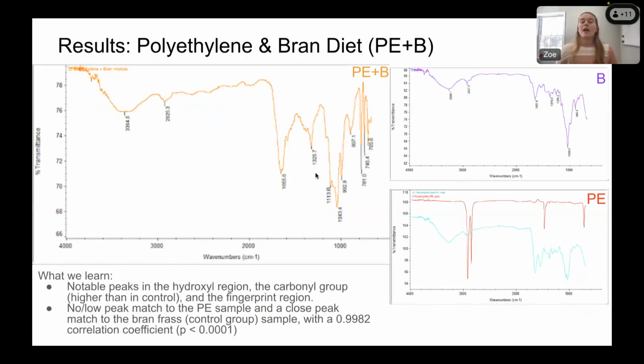The polyethylene and bran mixture, however, had the same peaks as the control group in the hydroxyl region and the fingerprint region, and the carbonyl group, which is a little bit higher than the control, as you can see here. And a very low peak match to the polyethylene group as compared to the bran group, which had a 0.9982 correlation coefficient.